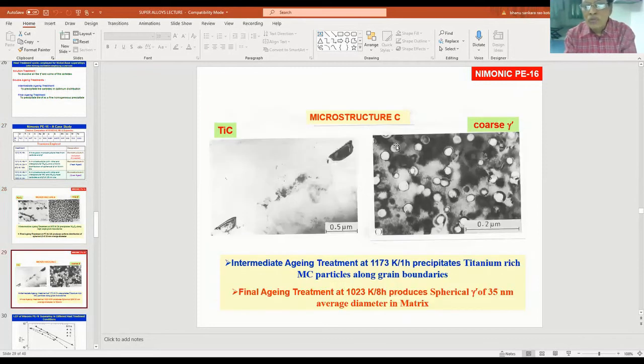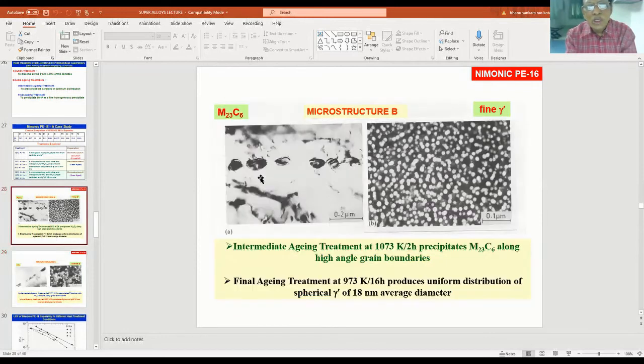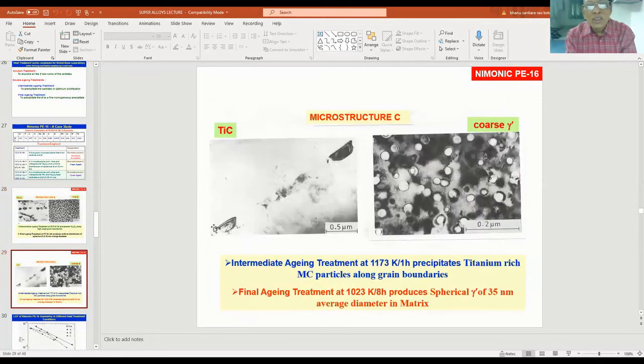When I have gone for microstructure C, where I use the high intermediate aging temperature, titanium carbide precipitates, you see the distribution of the precipitates. In the previous microstructure, they are discrete and uniformly distributed. But in this case, the shape also differed and they are widely spaced. You see the gamma prime also got coarsened because I have used the higher aging temperature. Why I have brought this to your notice is that your composition is fixed, but you can vary your properties by giving different heat treatments.